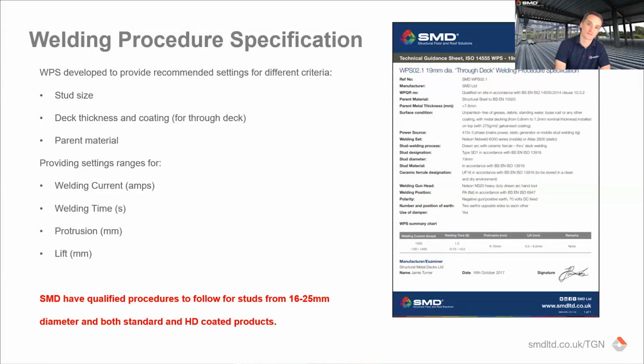And we have these WPS, as it's called, for 16 up to 25mm diameter studs, because you can weld direct to steel, and we have them for direct to steel. We also have them for both a standard coated deck, through deck, and a HD coated product. So HD is our high durability deck, so it's got a better coating, which means the coating's slightly thicker, which means your settings generally have to be slightly different. So we've got qualified weld settings for that.